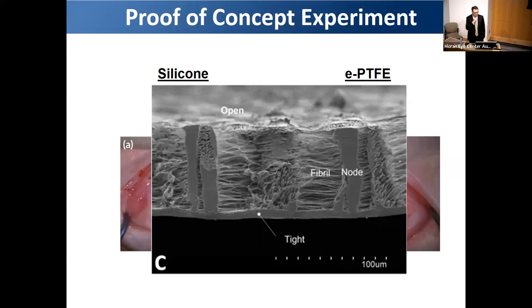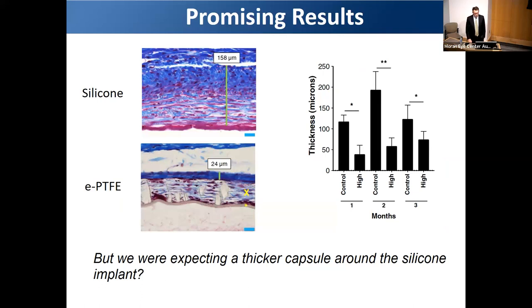The hypothesis was that this would create a thin capsule with permeable surrounding tissue. Looking at histology, we saw cell integration and a thinner capsule — capsules around silicone implants measured about 150–200 microns while those around ePTFE implants were less than 50 microns, seen out to three months.